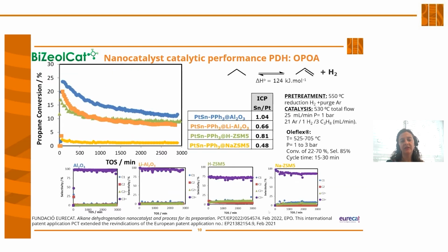When looking at the catalytic performance, in this case for the propane dehydrogenation, what we could observe is that we have conversions similar to those of the benchmark process. Moreover, the conversion can be related to the tin platinum content on the catalyst, and as we can see, for the highest tin contents we can observe the highest conversions, while the selectivity is very high, and in the case of the aluminas, almost 100%.